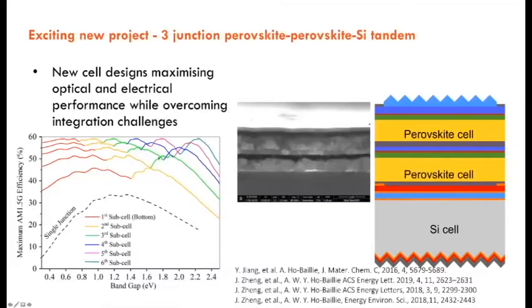So you can see that there are a lot more layers, there are a lot more interlayers, and therefore it's a lot more fiddly to integrate all those cells together. So it's easy to draw it on a cartoon, but actually making the cell, in the process not damaging the cells and also having efficient transport between the layers, is quite tricky. Also, optically, we have to optimize the layers because they all have different optical constants, and also electrically as well. And as we move on to larger areas, we've got to think about metal grid designs and optical losses and shading losses, etc.